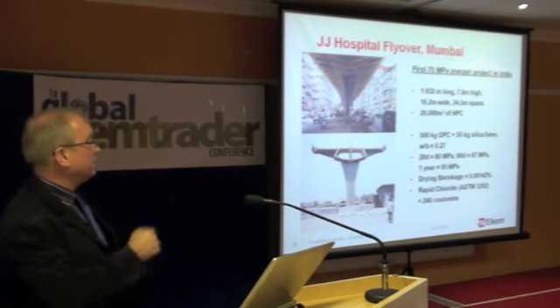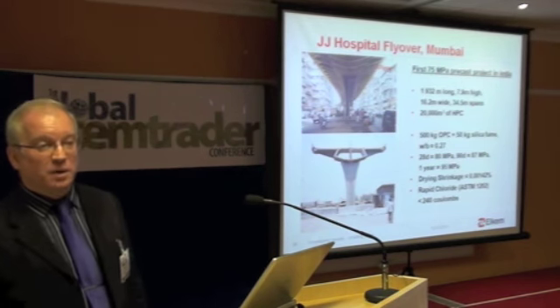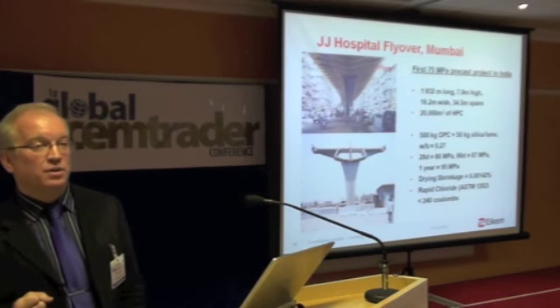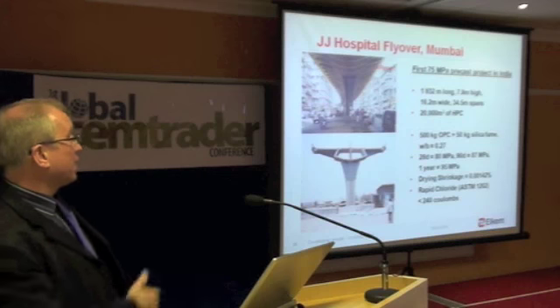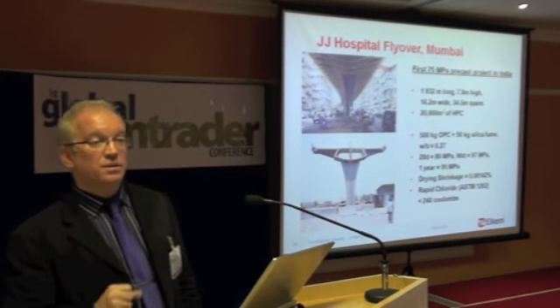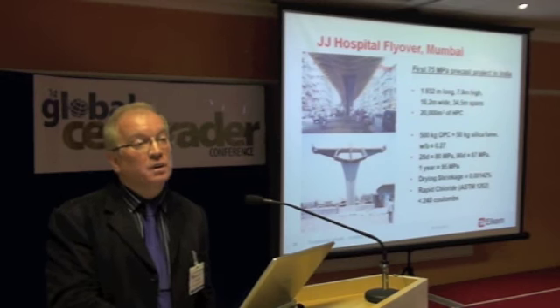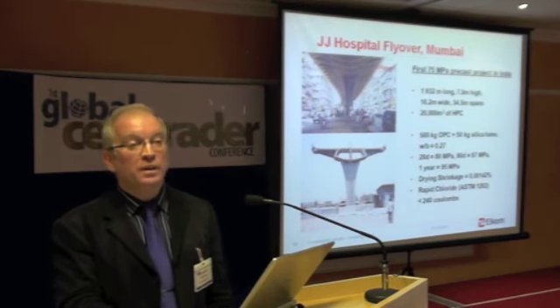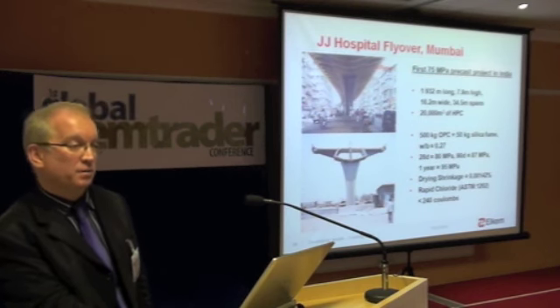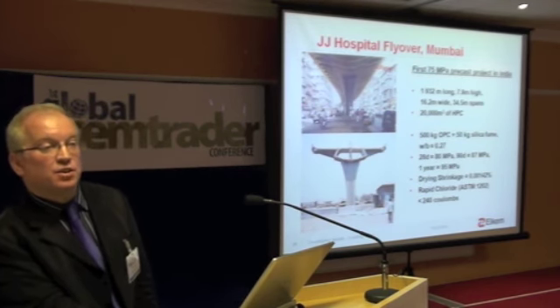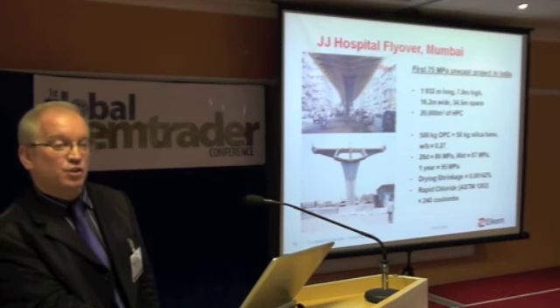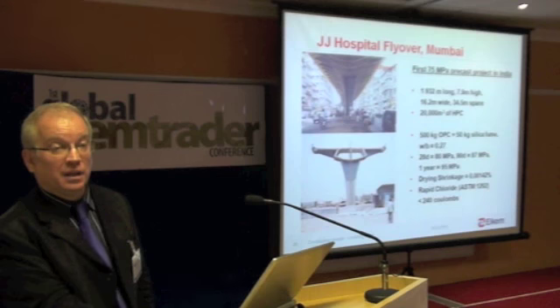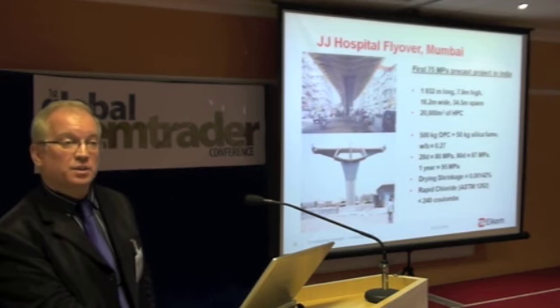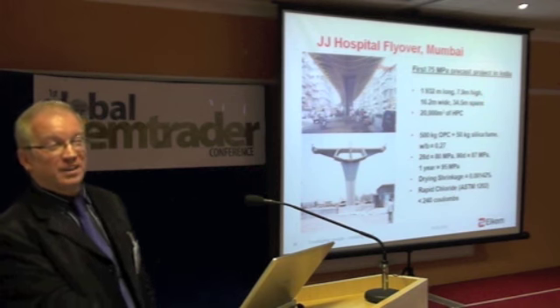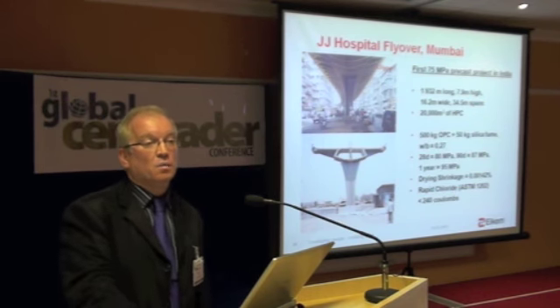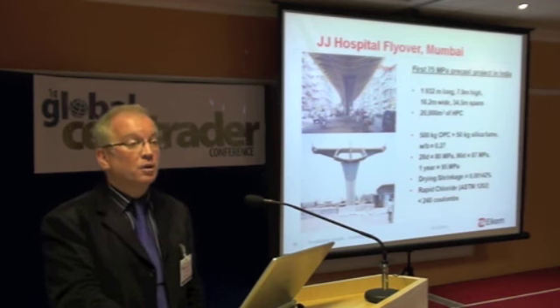This is the other project in India where they first specified 75 megapascal. This was about 5 years after I'd been trying to persuade them to change the concrete technology, and they did. It's a very strong mix, as you can see from the design there, but look at the numbers that were achieved. At 1 year, that's gone up to 95 megapascal. The chloride resistance is less than 240 coulombs. That's negligible chloride attack on that concrete. They're in the middle of town, but there's still enough pollution there to warrant that sort of durability. Drying shrinkage less than 0.001. This is incredible quality of concrete.